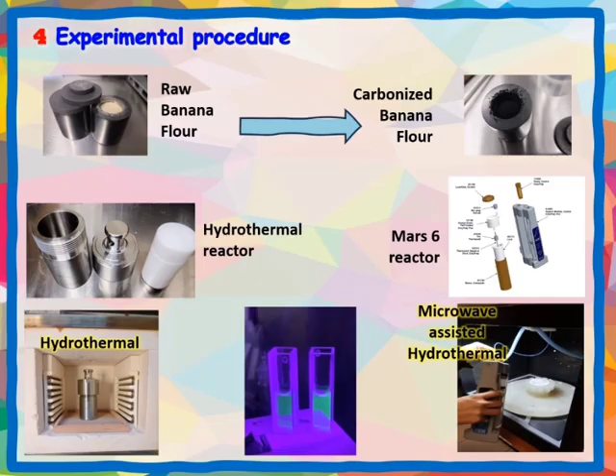On the right side, the reactor used in the Mars 6 equipment is a Teflon container with a fiberglass reinforcement. The lid has holes for the fiber optic temperature sensor and another hole for sensing pressure. The reactor is placed in a cartridge that holds it in position on the rotating platform. In the center, the product, the carbon quantum dots, can be seen. When illuminated with ultraviolet light, they emit wavelengths very close to each other. This will be verified later with photoluminescence spectroscopy.